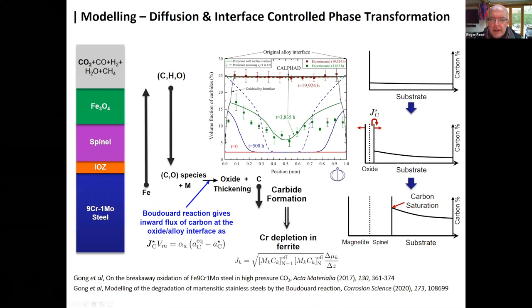And you can see here from the evidence presented in this graph that when one goes across the fin, so this is again 1 millimeter, the length scale here, and one plots the volume fraction of the carbides, eventually, I think this data is for 600 degrees Celsius, so I apologize this isn't on this graph, but eventually the fin becomes totally saturated with carbon or carbide, corresponding to an activity of one. Okay, but this actually takes some time to occur. And moreover, one has to acknowledge the destruction of some of the underlying metal.